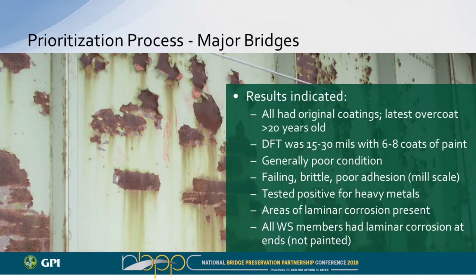They all tested positive for heavy metals. So we knew we had lead, a high percentage of lead with the primer. We also had cadmium and chromium. So we got hazardous metals. With the condition as you see here, a lot of these bridges cross through urban areas, even suburban areas to a certain extent, and you've got these releases, these environmental contaminations of this lead-based paint, really became an issue.